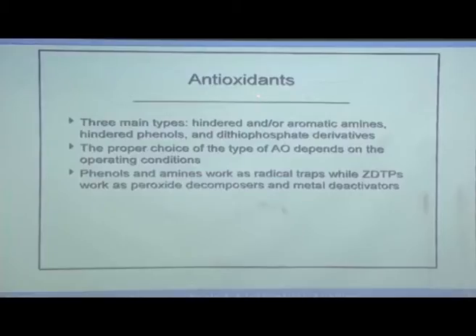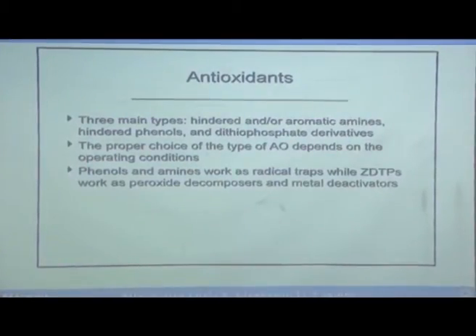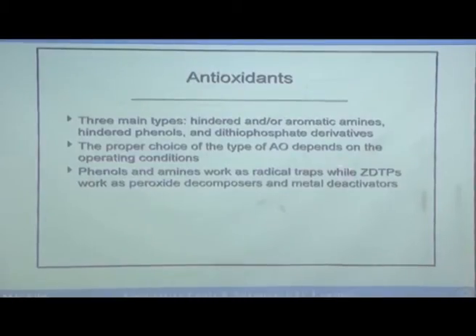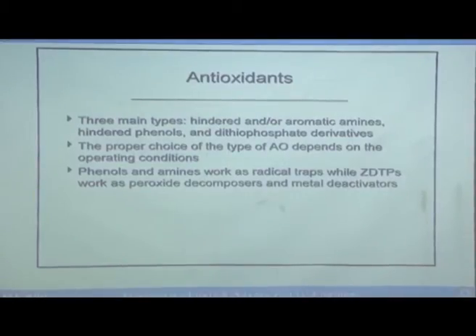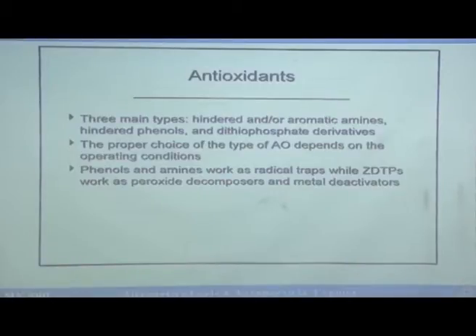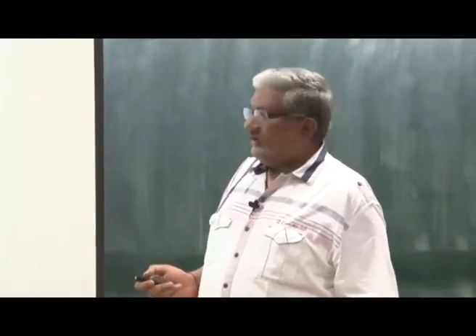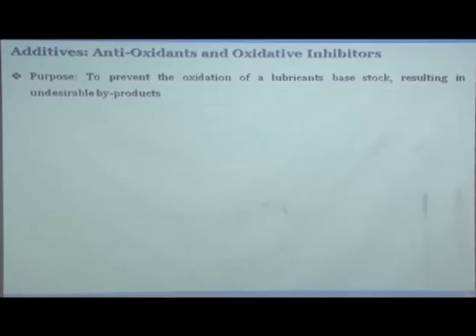There are three main types of antioxidants: hindered aromatic amines, hindered phenols, and dithiophosphate derivatives. The proper choice depends on the operating conditions the oil is exposed to. Phenols and amines work as radical traps, while ZDDP works as a peroxide decomposer and metal deactivator. Depending on what kind of attack you expect — what species will oxidize your base stock — you make the choice of which chemical to use as antioxidant.